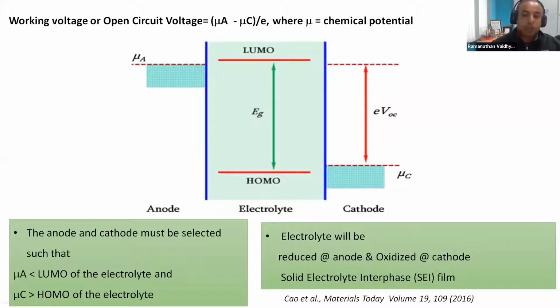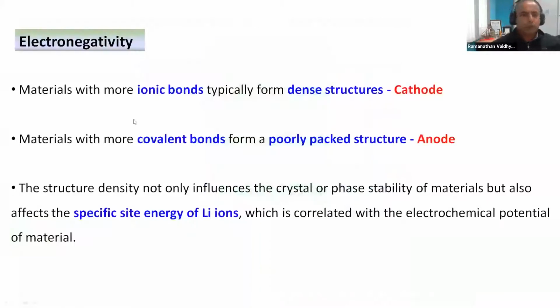But at the same time, you do want some amount of the SEI layer to be able to provide smooth transport of charges at the interface of electrode and electrolyte. And why is this important? Because in a COF, since it's a modular structure, you can tune your monomers' electronics to really achieve these exact energy levels that match with the electrolyte. And you can also have a variety of choices of electrolytes by tuning the chemical potential of your COF-based anode or cathode.